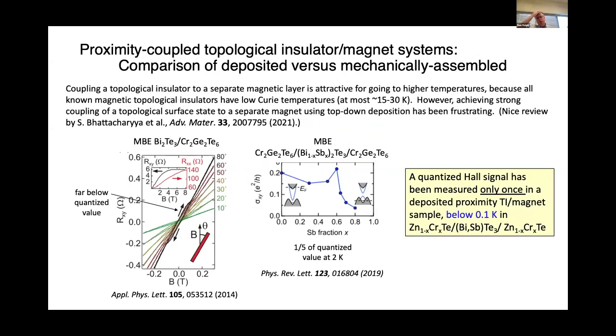So it's attractive to see if you can get higher temperatures by combining a higher temperature magnet with a topological insulator. You can get magnets with Curie temperatures well above 10 Kelvin or so and try to integrate those with topological surface states. And that's been tried by quite a few groups, but really it's been surprisingly disappointing what you see. There's only one case I know where people have seen a quantization of a Hall signal, and that was below 100 millikelvin.